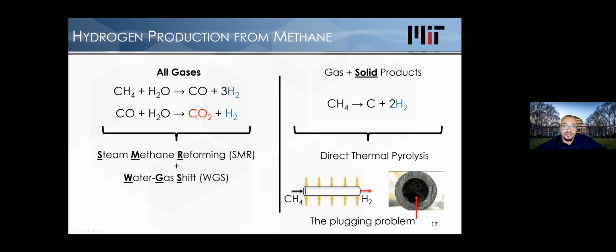You'll plug your reactor. Now, the reason this is particularly bad is because it's uneconomical to imagine running this in some batch reactor, where you heat up to 1400 C, flow for a little bit, make some carbon and hydrogen. Now you got to cool the whole thing down, waste all that heat, get a plunger and plug out the graphite or all the carbon that you've got, and then heat it up again. That would be a very painful process, very uneconomical. So one key thing with this is, how do you solve the plugging problem? How do you get rid of all this carbon that would block the reactor?